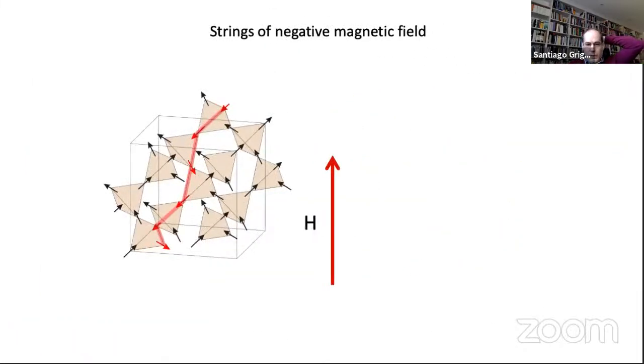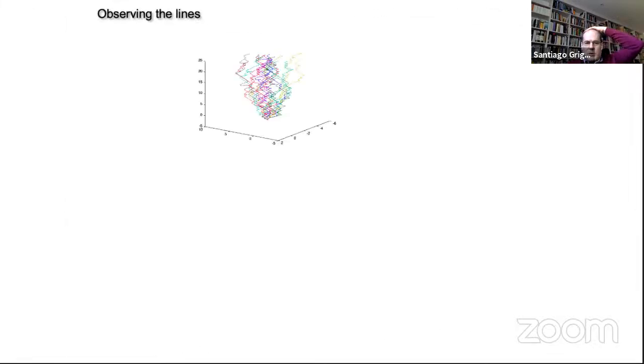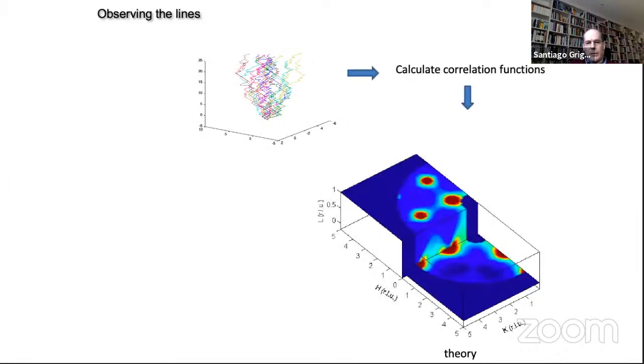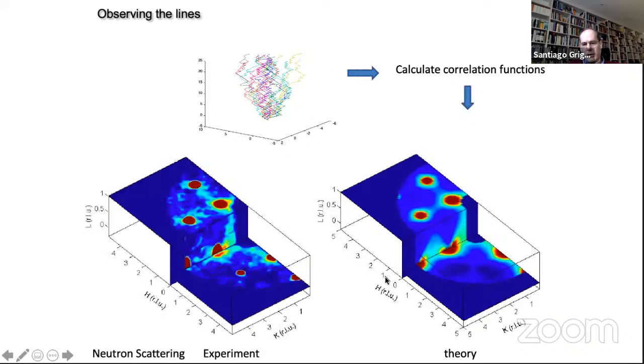So in a sense, I would say that these are not completely unlike vortices in a high TC superconductor, although they would be like the opposite of vortices, in the sense that this is decreasing the magnetization rather than increasing. Okay, so going back to the idea on whether one can get some sort of direct observation of these lines, you see that because you get these sort of random walks along the field direction, now you can calculate the correlation function for that, and this is what you get, and you can compare that with the experiment. And again, within the noise of the experiment, it's not too bad.